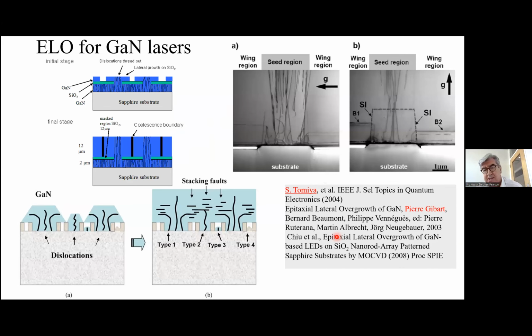Now, there are some tricks. It's okay to make blue LEDs with lattice mismatched structures, but to make a laser, you still have to have a low dislocation density. And there were some tremendous materials breakthroughs to get the low dislocation density. The trick by Tomiya from Japan and Gibart from France was to do what is called epitaxial lateral overgrowth, where you grow the gallium nitride for a few microns on top of a sapphire substrate.